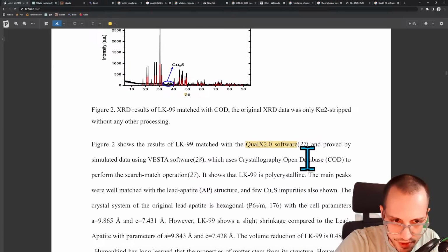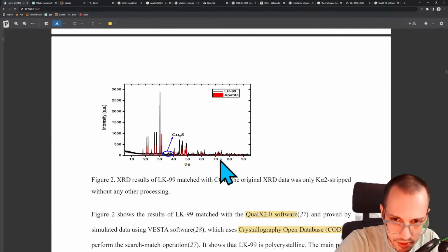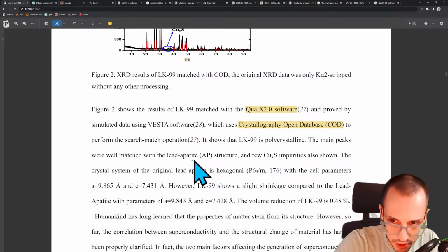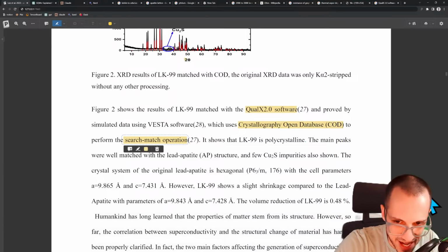Uses crystallography open database to perform the search match operation. It shows that LK99 is polycrystalline. Okay, so there's some kind of open database of results from X-ray diffraction, and then they searched through this entire database to find a match. And that match is what is telling them that LK99 is polycrystalline. So the main peaks are well matched with the lead apatite structure, and a few Cu2S impurities are also shown. Okay, so the copper is actually a form of impurity.